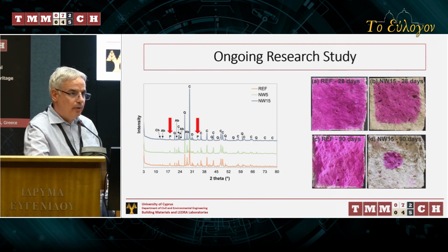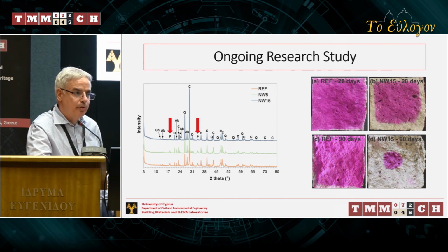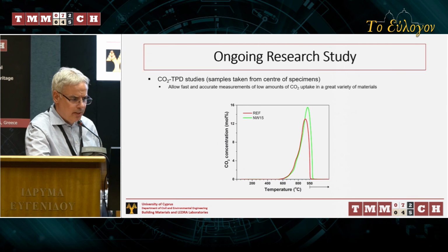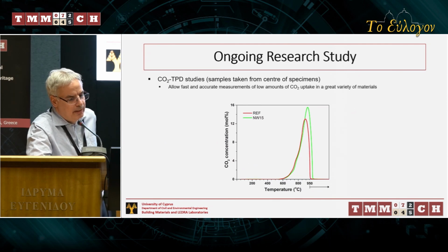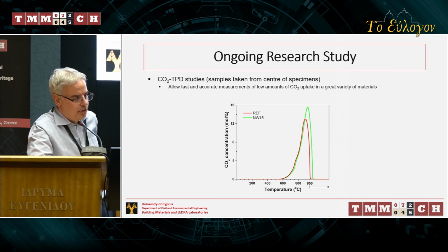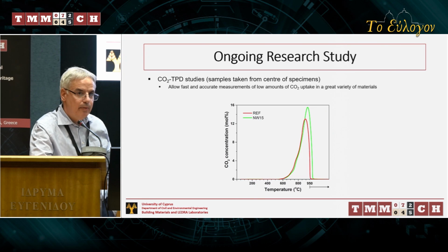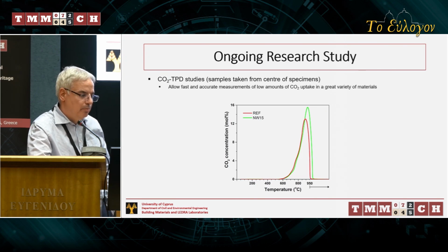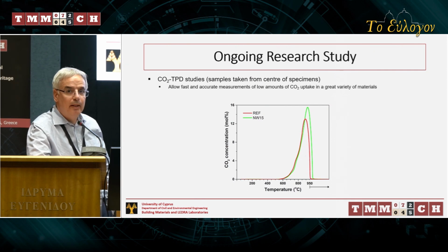And this was also confirmed by some tests with phenolphthalein, by which the sample with the quarry waste additive was almost fully carbonated after 90 days, as opposed to the reference sample, which showed only slight evidence of carbonation. And all this in natural conditions without any accelerated carbonation. We also carried out some CO2 chemisorption followed by temperature programmed desorption experiments, which allow fast and accurate measurements of low amounts of CO2 uptake in a great variety of materials. And again, these tests confirm the potential of the mix design with the quarry waste additive to sequester greater amounts of CO2 compared to the reference sample.